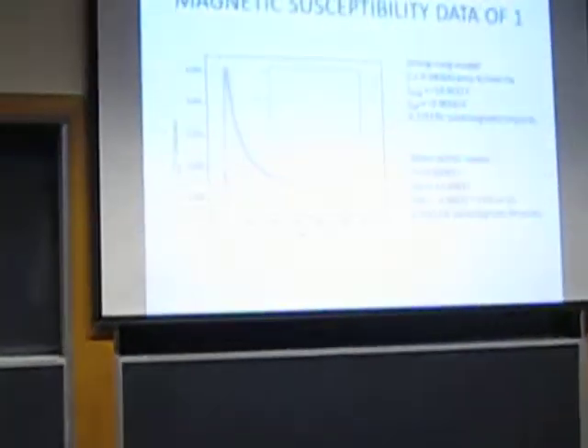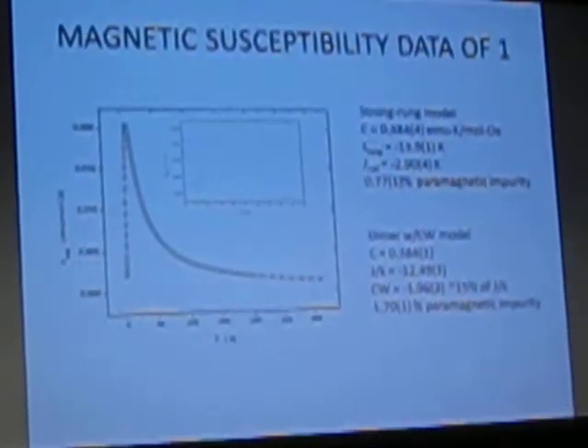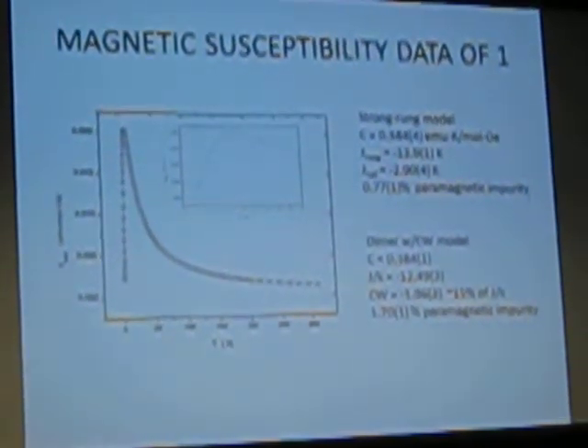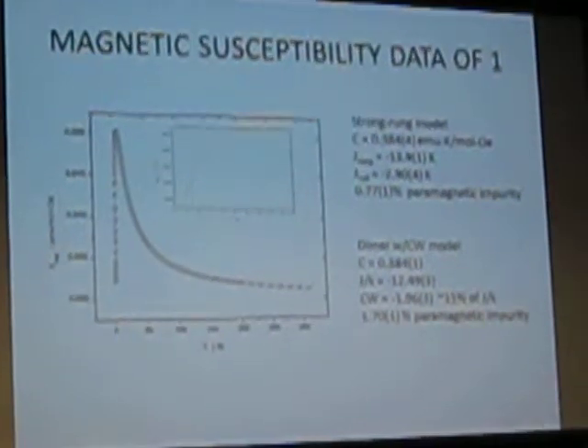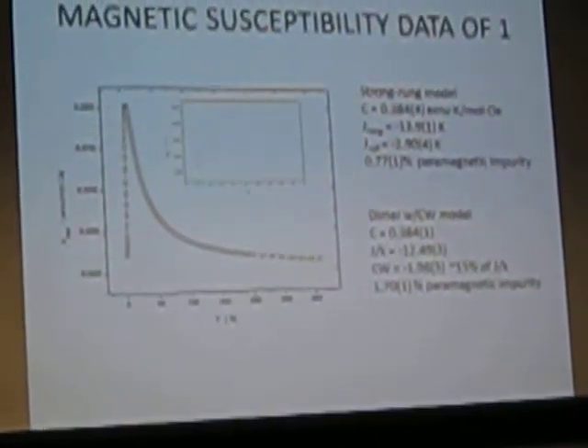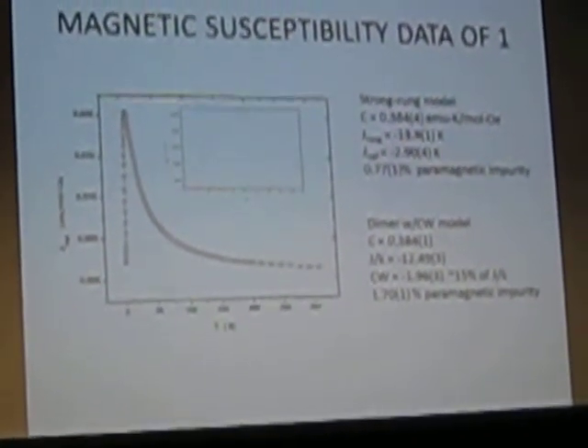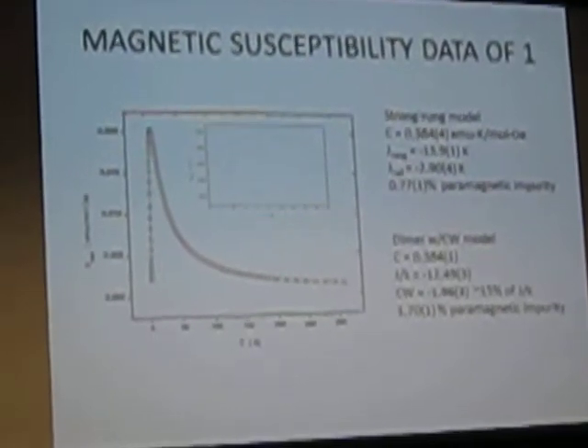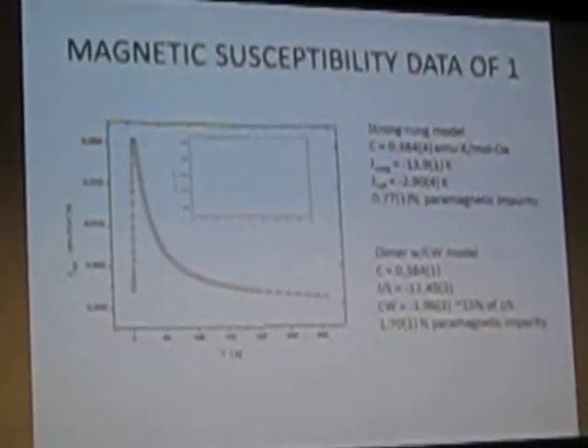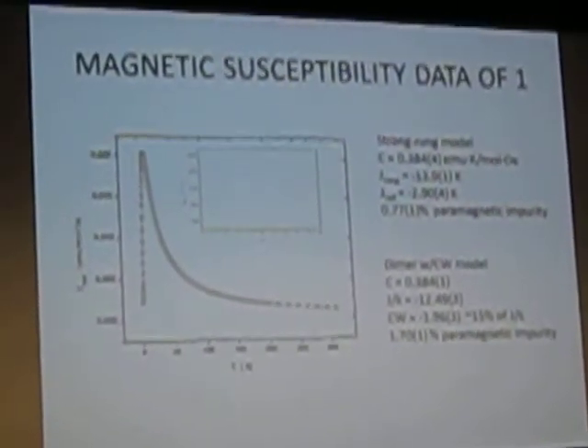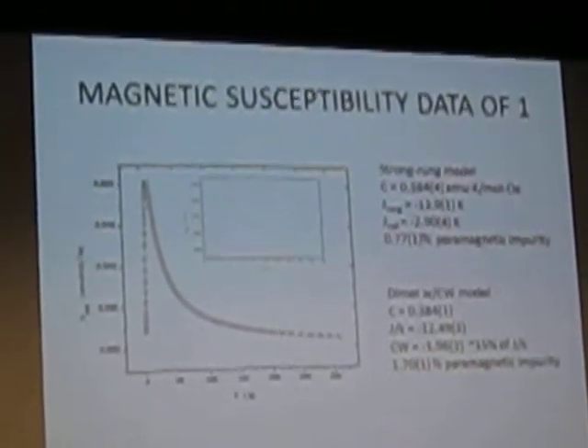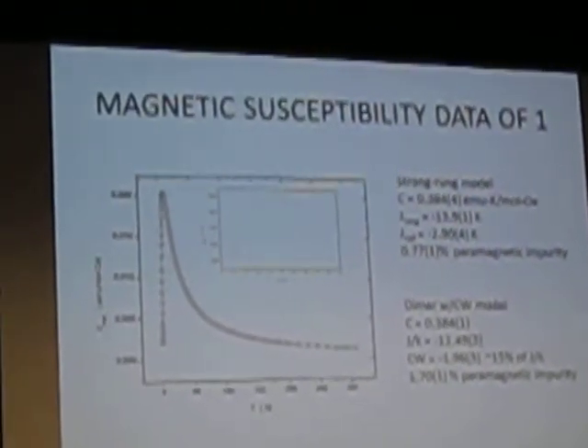So what does the magnetism say? Well, we took the variable temperature magnetic susceptibility data. As you lower the temperature, you reach a maximum in Chi at about 10 Kelvin, and then after 10 Kelvin, it drops towards a value of 0. So this is indicative of a singlet ground state, so a spin gap compound.